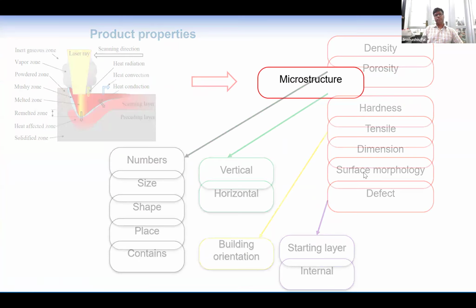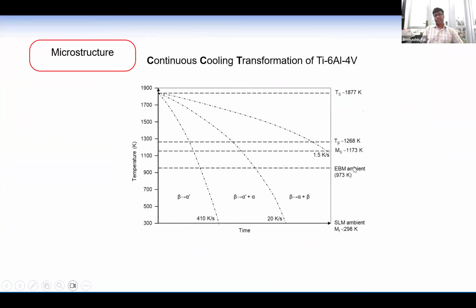So let's go through microstructure, how it can be controlled. For electron beam melting, there is actually an elevated temperature of the processing chamber, about 700 degrees centigrade. So the cooling rate will be slow. The microstructure will be different there, compared to the cooling rate of selective laser melting.